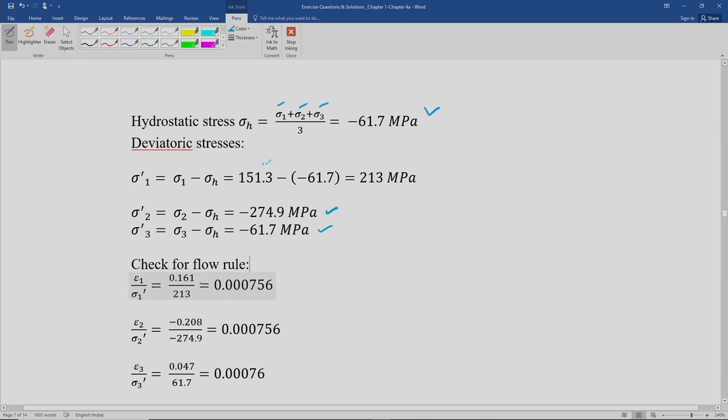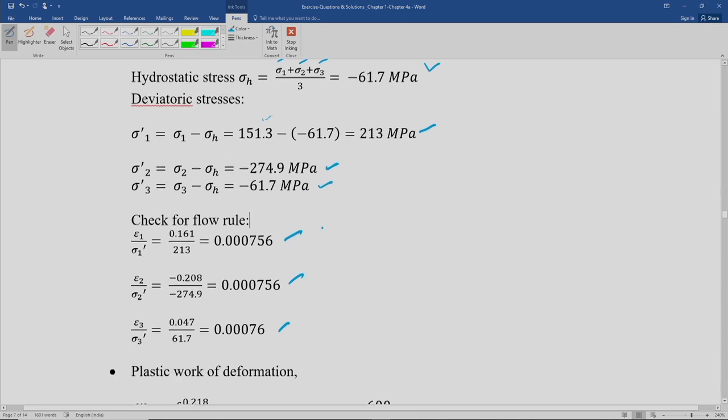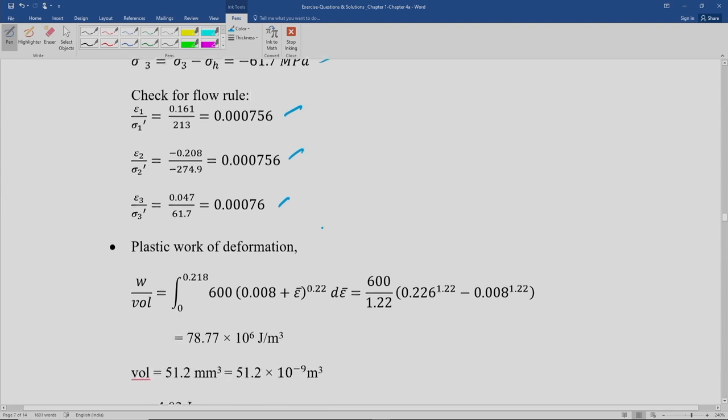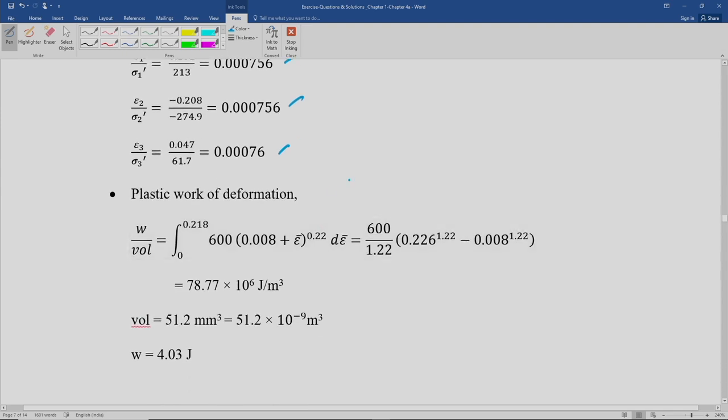So you can calculate all these ratios and you can check all these things are almost same. Epsilon 1 is known, sigma 1 dash is known here. Epsilon 2 is known, sigma 2 dash is known here. Epsilon 3 is known, sigma 3 dash is known here. If you calculate it, the ratio is going to remain same. So Levy-Mises flow rule is checked. Plastic work done, there is a last equation. So again we know that work done per unit volume is nothing but I am going to write sigma bar d epsilon bar, integral of that,